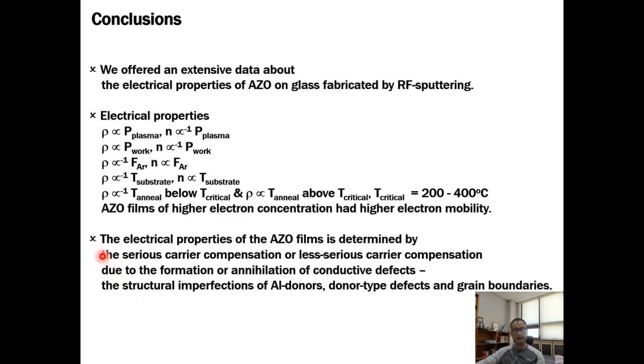It was suggested that electrical properties of the AZO thin films are determined by a serious carrier compensation or less serious carrier compensation due to formation or annihilation of conductive defect, like structural imperfection of aluminum donor, donor-type defect, and grain boundaries.